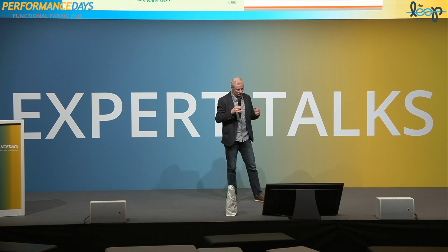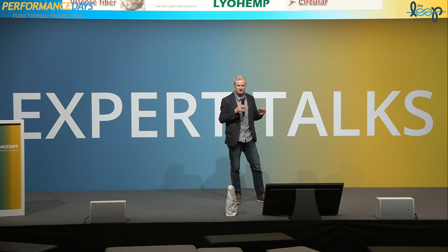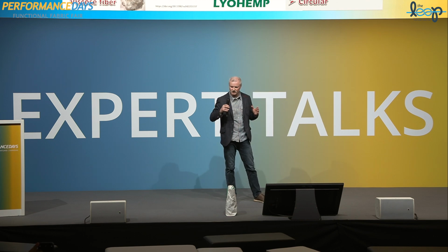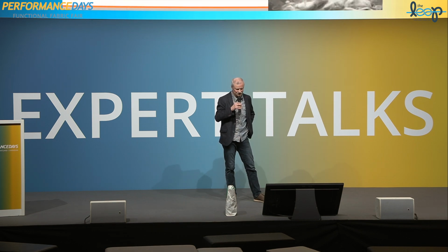We have partners to produce this pulp from the hemp plant, and we use the lyocell process. That means we have a circular process. We start with a biodegradable material like wood or even hemp. We can dissolve it in a physical way and not in a chemical way as it is done in the viscose process. The lyocell process is only a physical dissolving process. You see there are much fewer steps in the process, and this is the key feature. We can use 100% hemp pulp in the process compared to other producers.